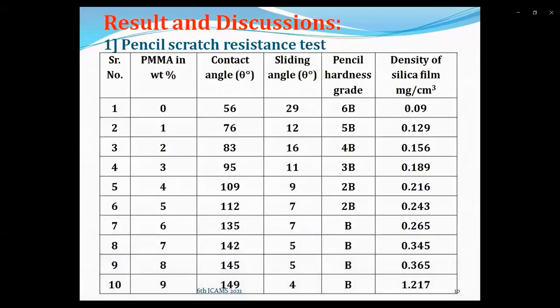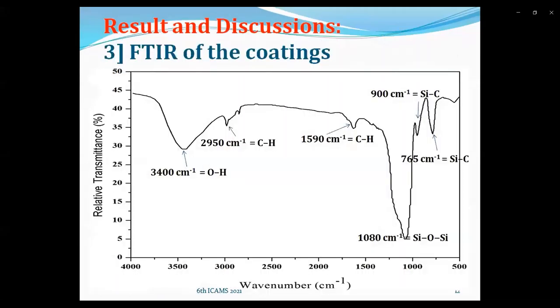So the results are as indicated in the table. This is the static water drop contact angle. The contact angle is 149 degrees. This is the FTIR of the silica coating exhibiting different functional groups in the coating. Then, the conclusion.